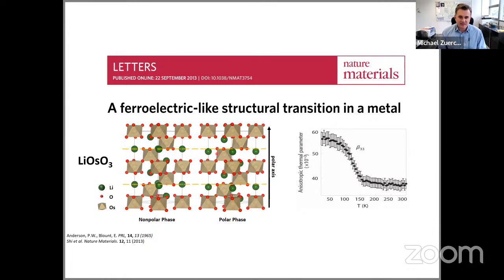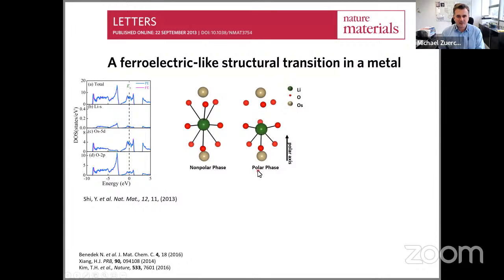However, for certain types of unit cells, and if you have a second order phase transition like that, Anderson and Blount already in 1965 predicted that these two properties can coexist in one material. Okay, it took almost 50 years, until 2013, when somebody was actually able to synthesize this crystal. So this was like 50 years in the making, from the theoretical prediction of this phenomenon until someone was able to make a crystal and confirm the properties. Okay, if we look at the unit cell of lithium osmate, what we have is the oxygen coordinated octahedrons of osmium, and we have the lithium, which in the polar phase is displaced along a polar axis that spans along the c-axis of the crystal, basically in the direction where the polar axis points between the lithium atoms in that unit cell.